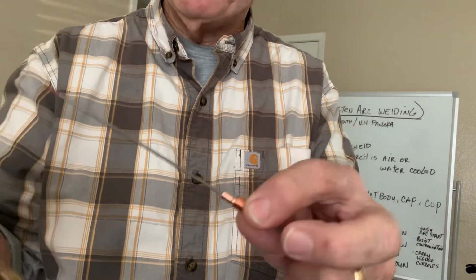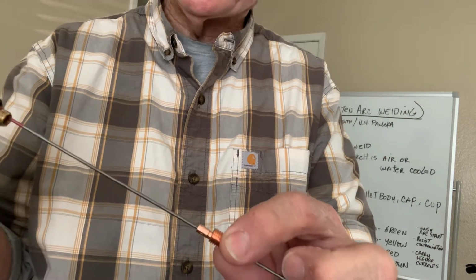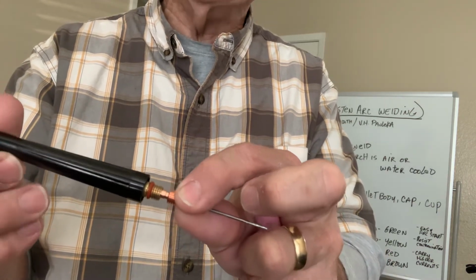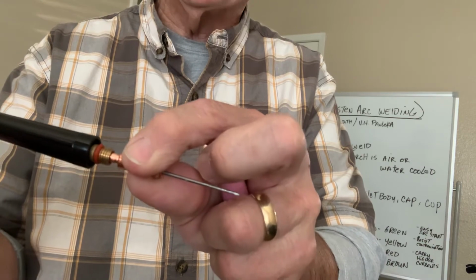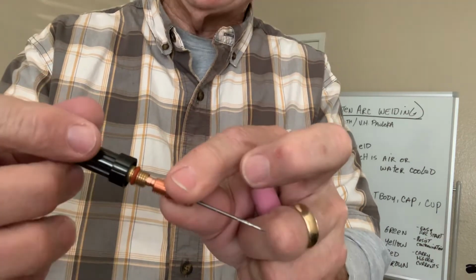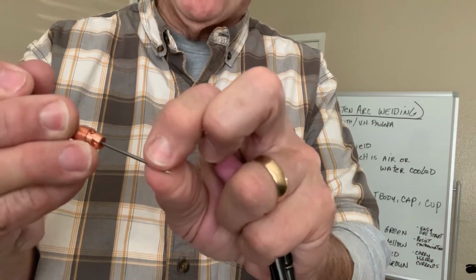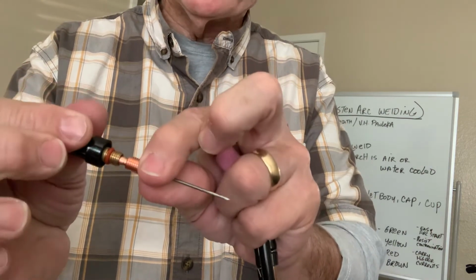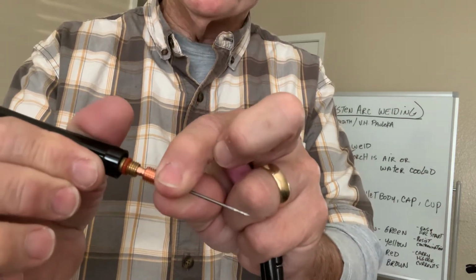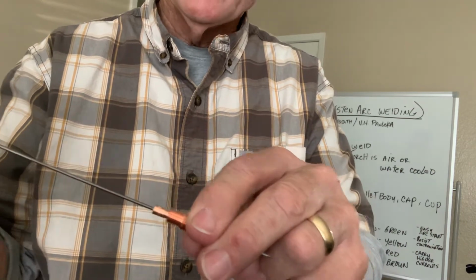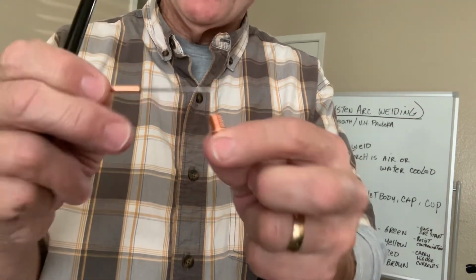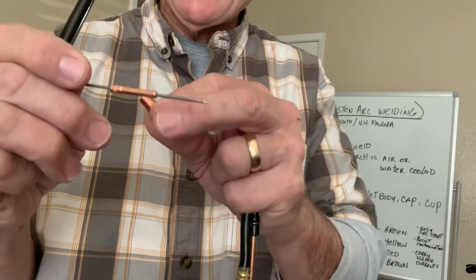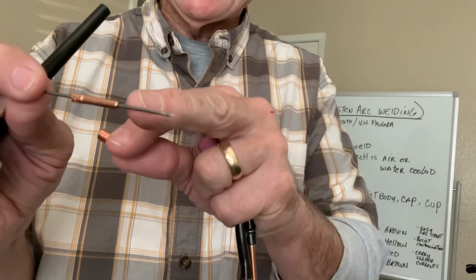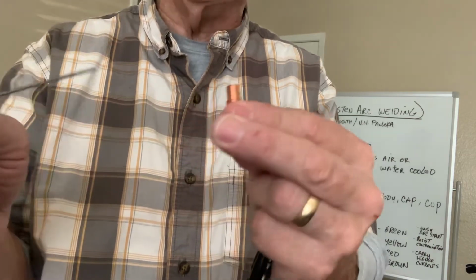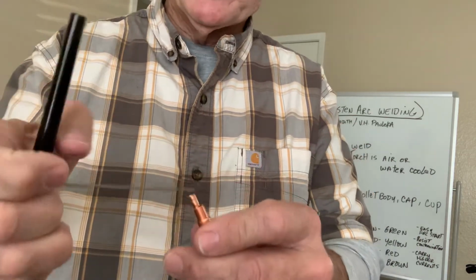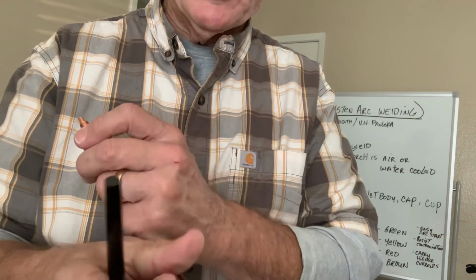I won't be able to tighten, because what ends up happening is that this cap goes on and it gets tightened and it pushes onto that collet, pushes into that tapered hole, and that's what actually holds this piece of tungsten in place, that push onto the collet itself. But just keep in mind that this collet body and the collet have to be the same size, and it has to be the same size as the tungsten that you're using, because this tungsten comes in different sizes.